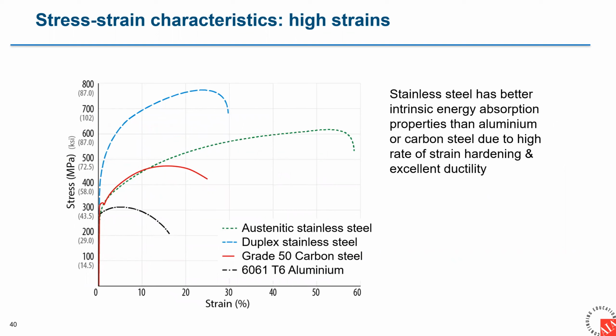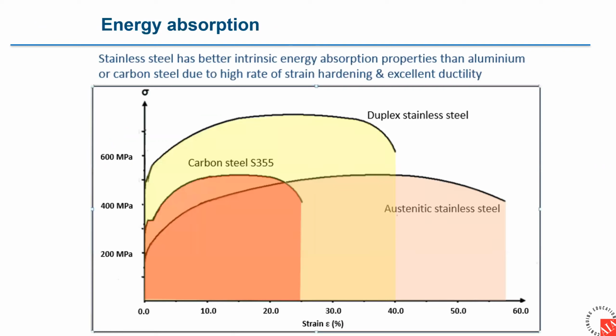As we carry the stress strain curves all the way out to failure, you can see that the area under the duplex and austenitic stainless steel curves is much larger than that for aluminum or carbon steel. That is an indication of the intrinsic ability to absorb energy. Aluminum and carbon steel are nowhere close to stainless steel. It's a result of strain hardening and the excellent ductility of stainless steel. This shows it a bit more graphically. You can see what those areas are under the curves. So the stainless steels are always going to be better in terms of energy absorption and ductility.